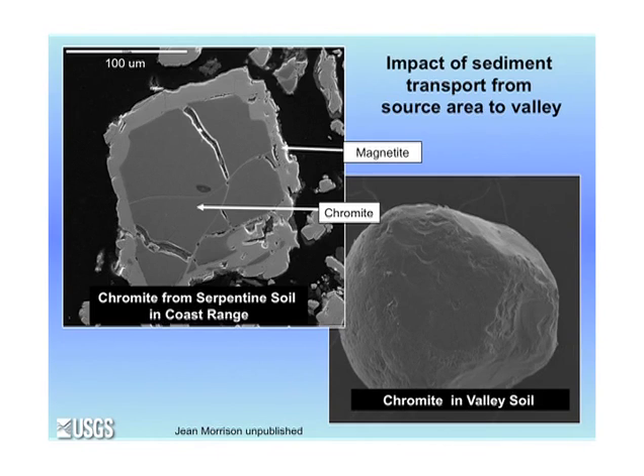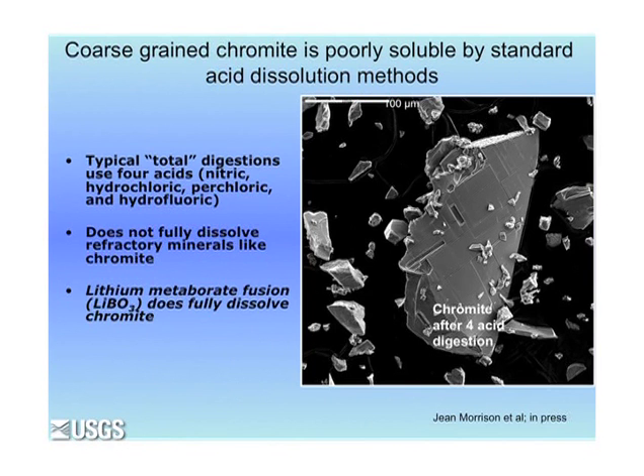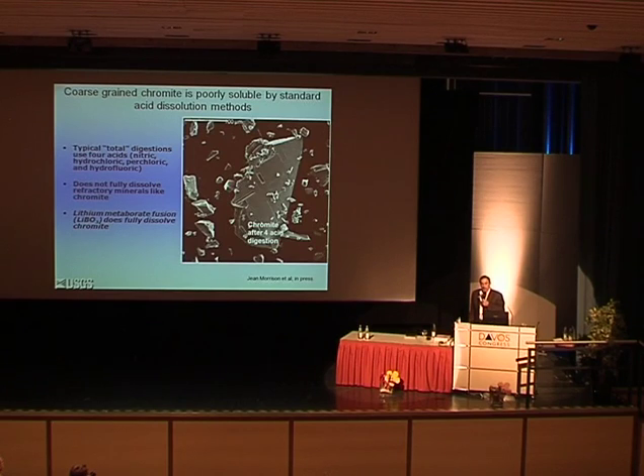By the time you get down to the valley, however, the magnetite rim is gone and chromite is exposed, thus potentially exposing chromium to pore fluids after downstream transport and abrasion. We can use another characteristic of chromite, its refractory nature, to get a little more insight into behavior of chromium during transport from the source area to the valley. Chromite is, like I said, refractory. The normal dissolution procedure we use for rocks involving four acids, nitric, hydrochloric, perchloric, and hydrofluoric, only weakly dissolves chromite, especially coarse chromite. On the other hand, if you fuse the sample with lithium metaborate, you get a total number.